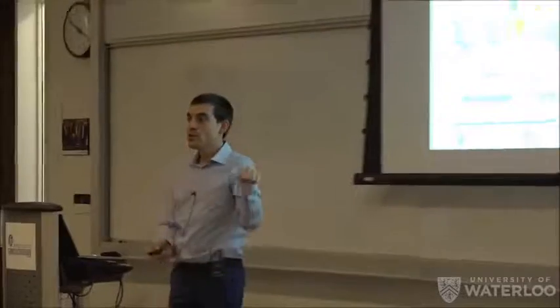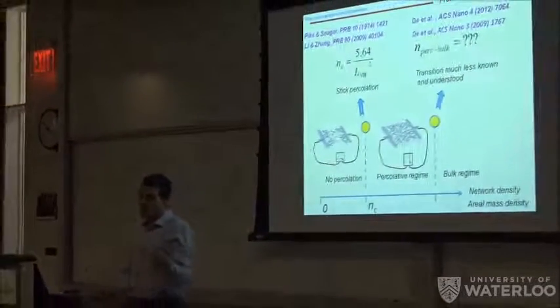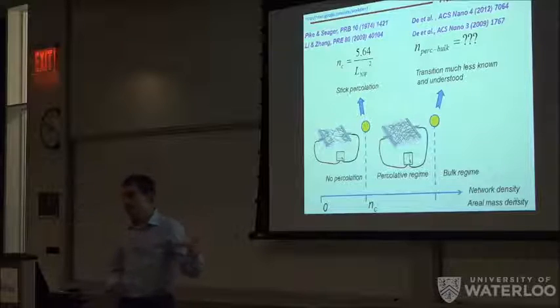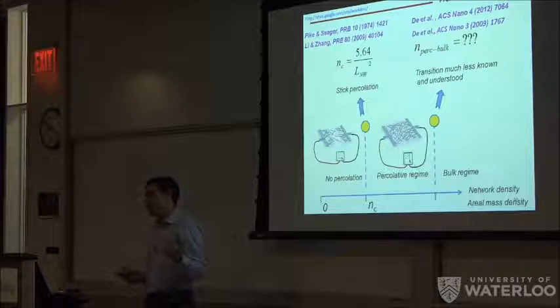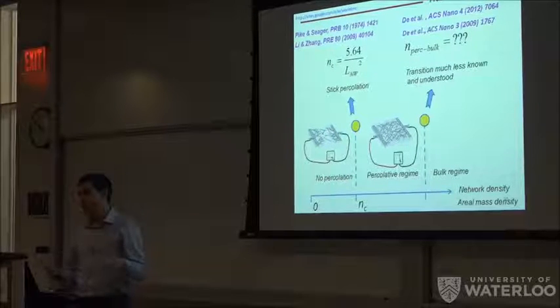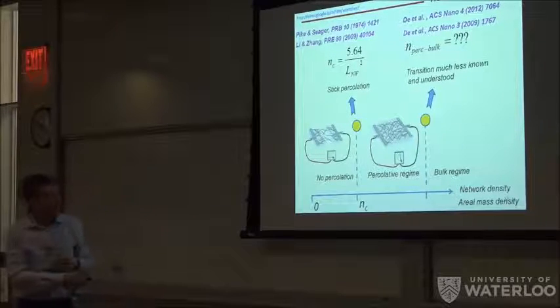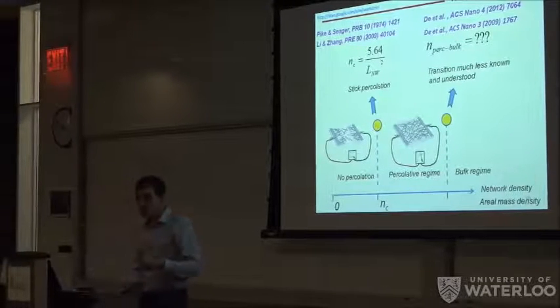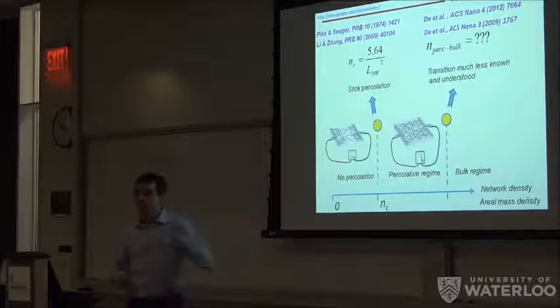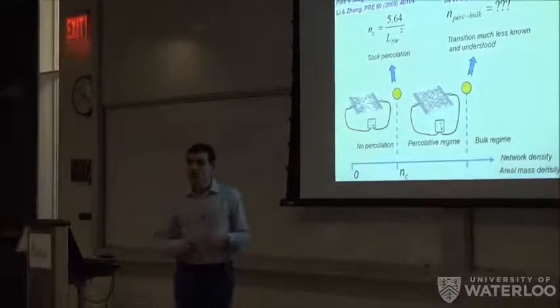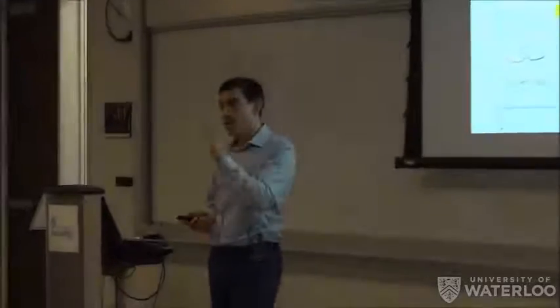These transparent conducting materials rely on a percolating network that ensures that the current can flow from one electrode to the other. If you increase the temperature too much, they are going to spheroidize, and then your connection is lost. So you need to prevent that, to make sure they are stable, even from the atmosphere. Silver is quite sensitive to sulfur. There's sulfur in the atmosphere, so if they are not passivated, they could react with sulfur, and we have observed that in some of our samples. And they could also spheroidize. This oxide coating just prevents that, and the exact mechanism we don't know for sure yet. But it helps release the heat or prevents this spheroidization. That's something we are currently studying.